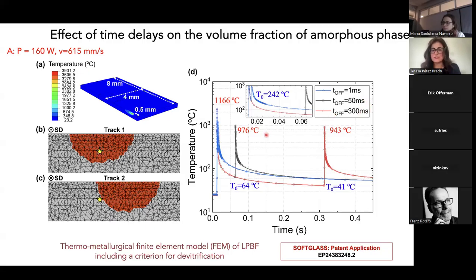So let us see the differences. Well, the first part is the same of course, for the three cases. So there is a first peak here, because these two peaks are very close together. We enlarged them here, we zoomed in a bit. So when we don't introduce time delays, the second peak is already here. And the T0, that means the temperature of the control point when the second laser pass comes, is around 242 Celsius. And then if we go to the other extreme, with a time delay of 300 milliseconds, this T0 goes down to 41 degrees C.